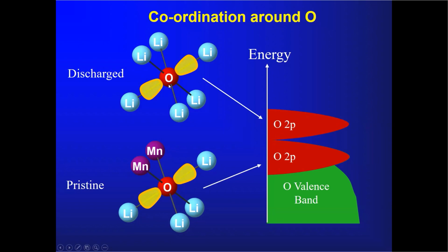Now, when one looks at the same environment at the end of discharge, now we have oxide ions where all of the surroundings are lithium. Remember, the lithiums go back into different sites, so the manganese is disordered, and these oxygens here are the oxygens that are now surrounded by lithium, not only in the alkali metal layers, but also now in a region of the transition metal layer. So now you have an oxygen you could regard as almost orphaned, because it's just got very weak interactions in terms of overlap of the oxygen 2p states with the lithium states. And overall, this pushes the oxygen states up further in energy. And this higher energy corresponds to a lower voltage.